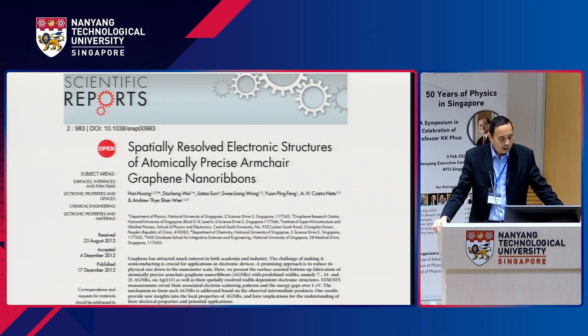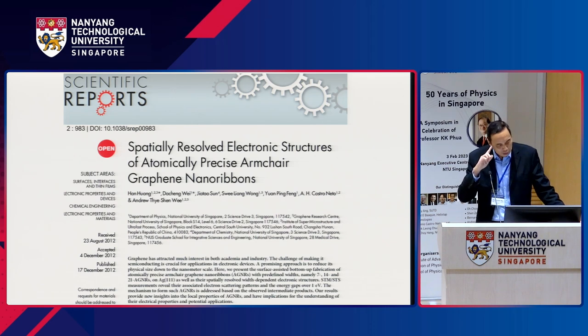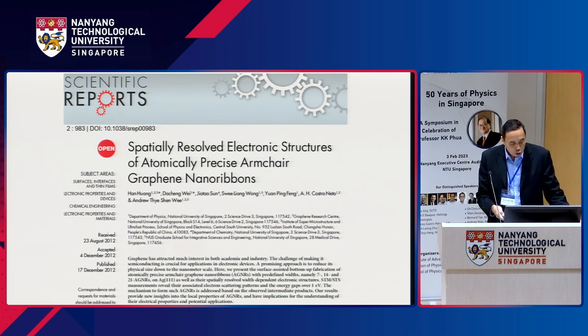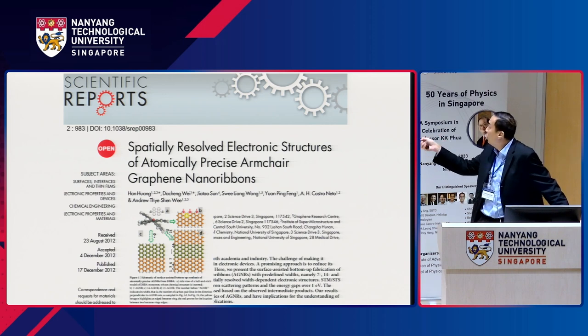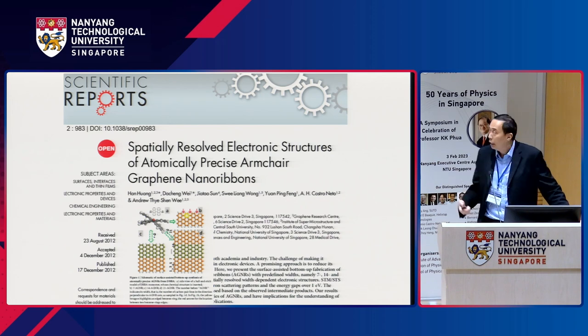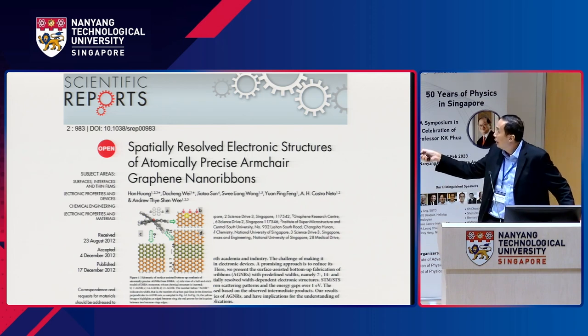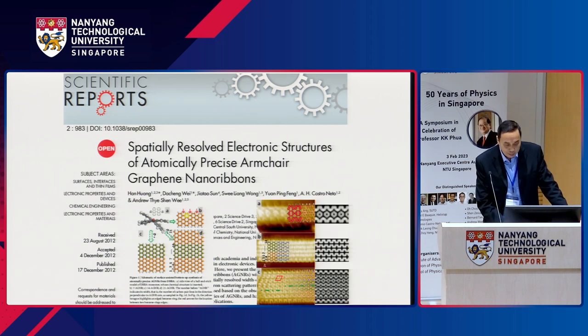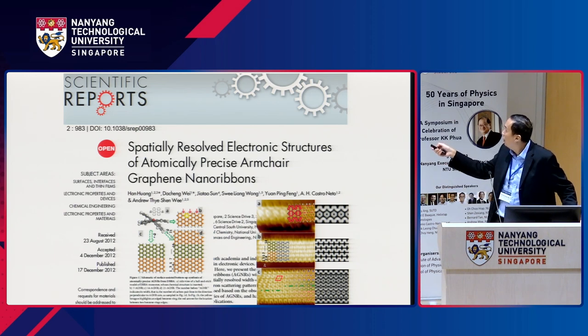So after the work done by, I forget the name of the group, we tried the bottom-up method of making spatially resolved armchair nanoribbons using this precursor molecule. This is molecular self-assembly. So we could form nanoribbons of different widths just by using this molecule. And because of the chemical structure of the molecule, you can guarantee that it's armchair in this case. So these are some STM images at low temperature of the electronic structures of these nanoribbons.